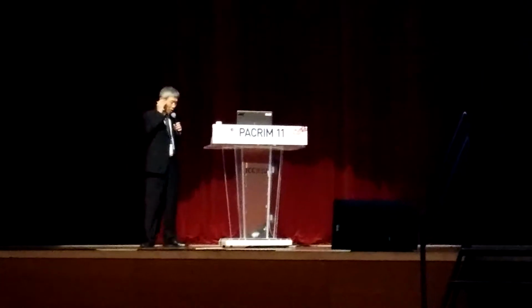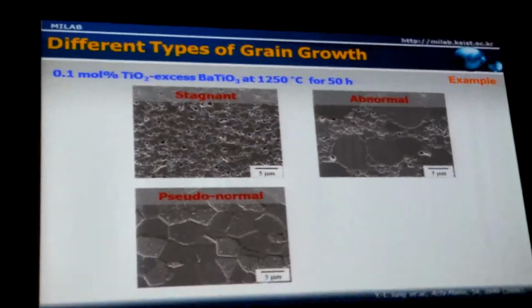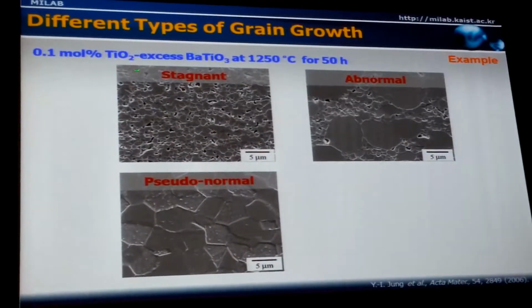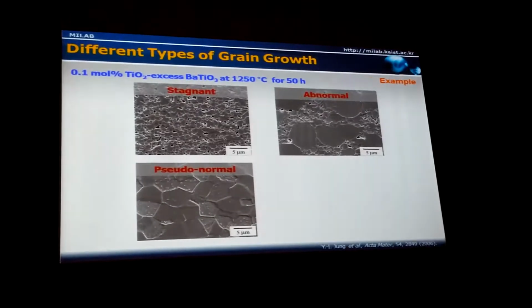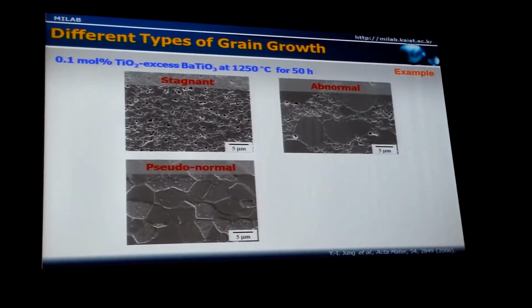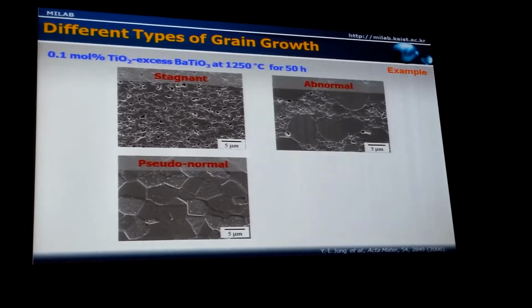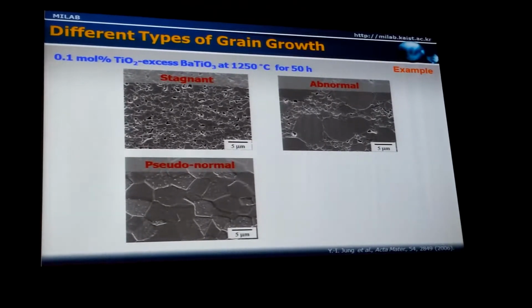Let me start by showing three different types of grain growth. Here you see three different microstructures. These microstructures were obtained from the same starting material, 0.1 mol% titanium excess barium titanate, and after the same thermal treatment. Nevertheless, the microstructures are very different.